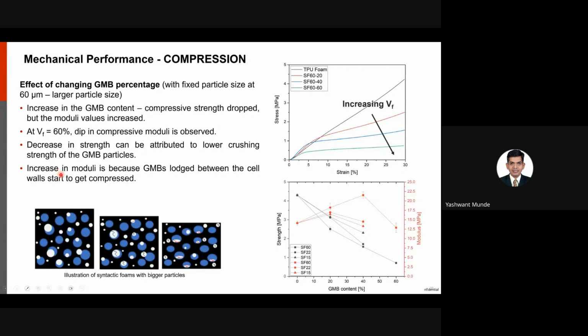Now, an increase in moduli was observed as we increase the volume fraction, but up to a certain extent. Here, please just focus on the square markers, because we're only changing the volume fraction for a fixed particle size. So up to 40% volume fraction, we see an improvement, but beyond that, we see a dip because there isn't sufficient matrix to bind this higher volume fraction of particles. And we see that as we reduce the particle size, the volume fraction corresponding to the peak value shifts to the left. That is, smaller particles create further disintegration of the syntactic foam.